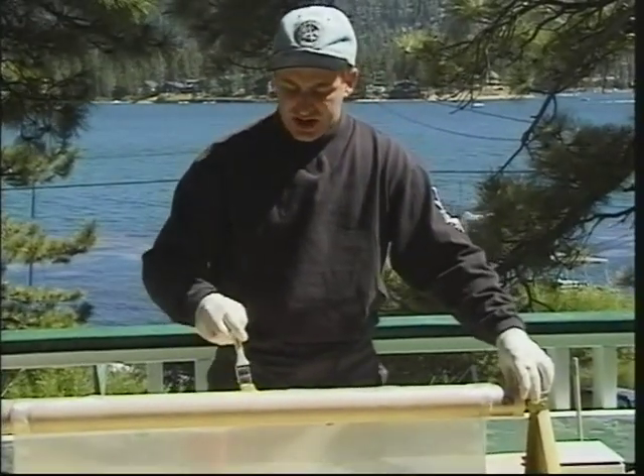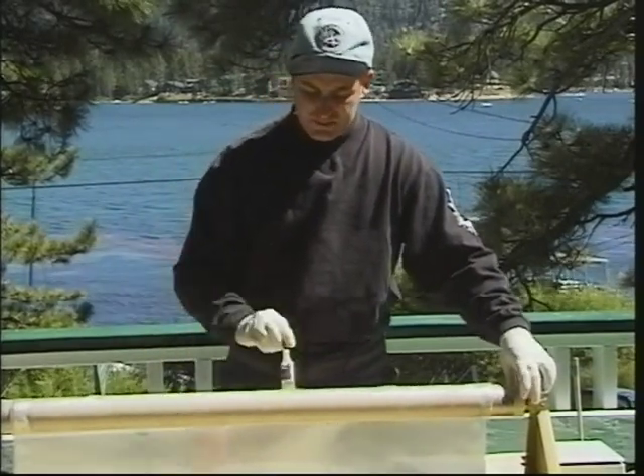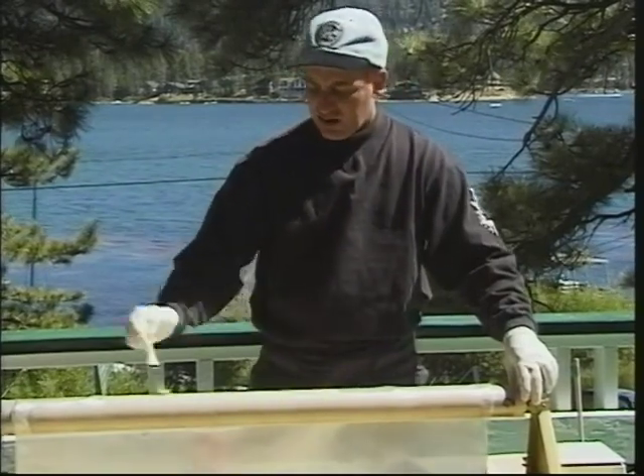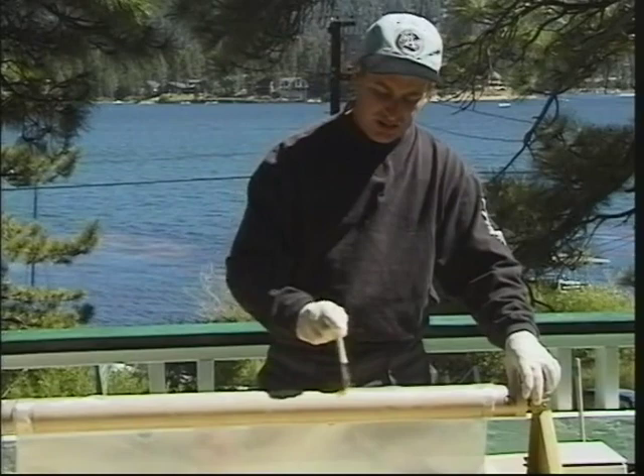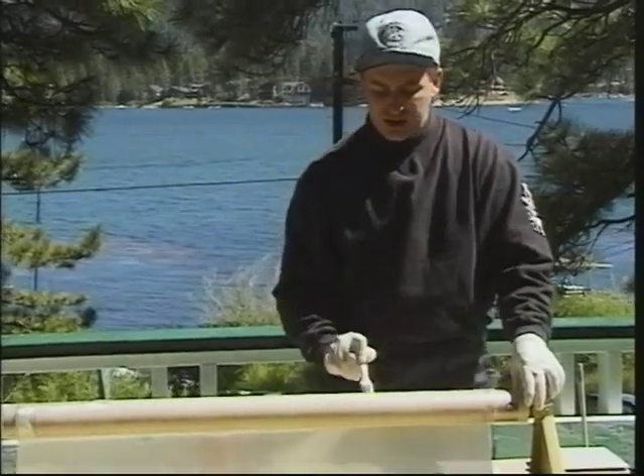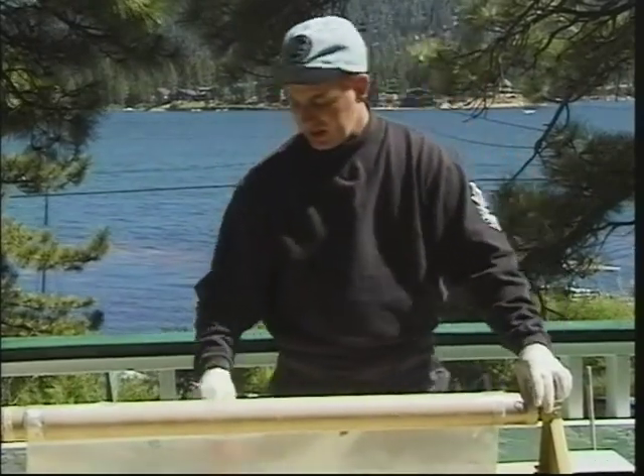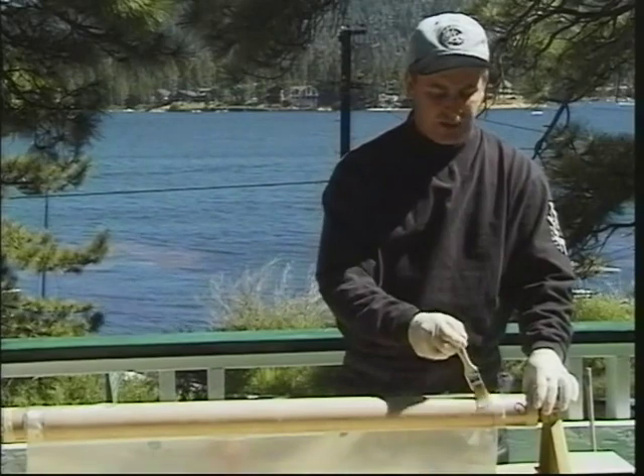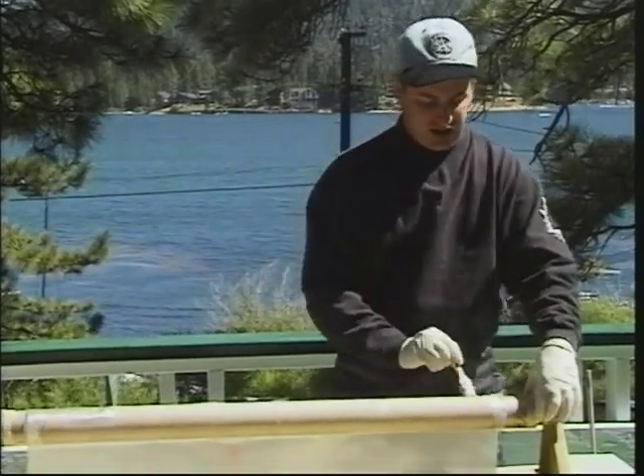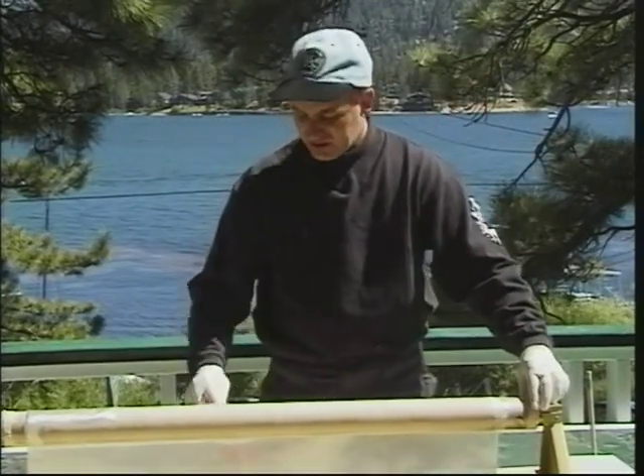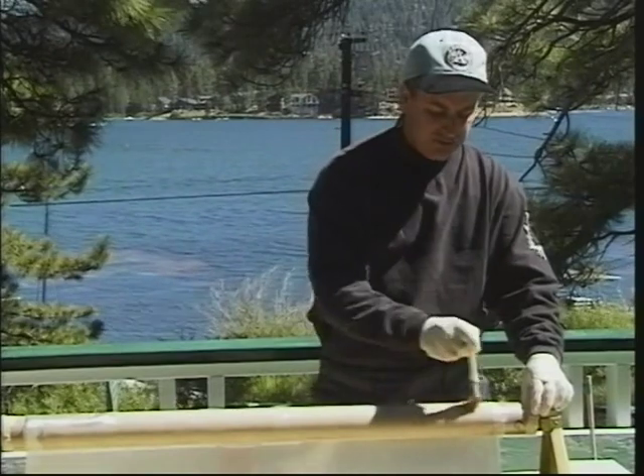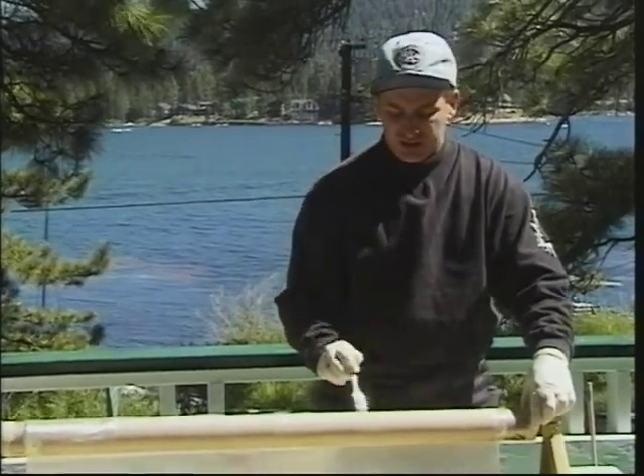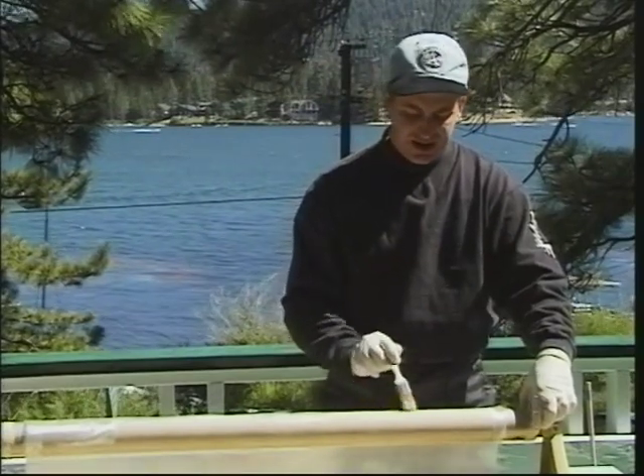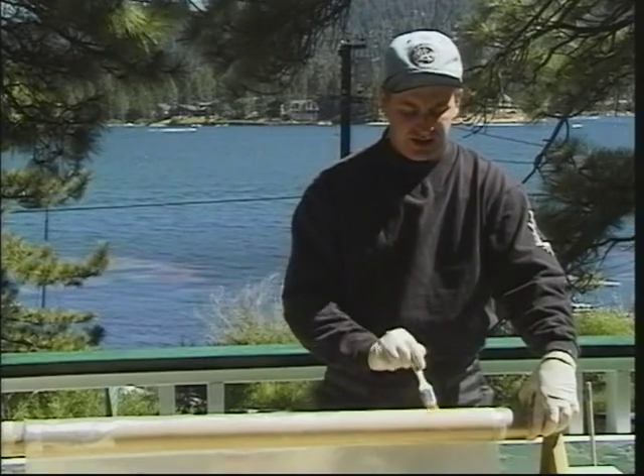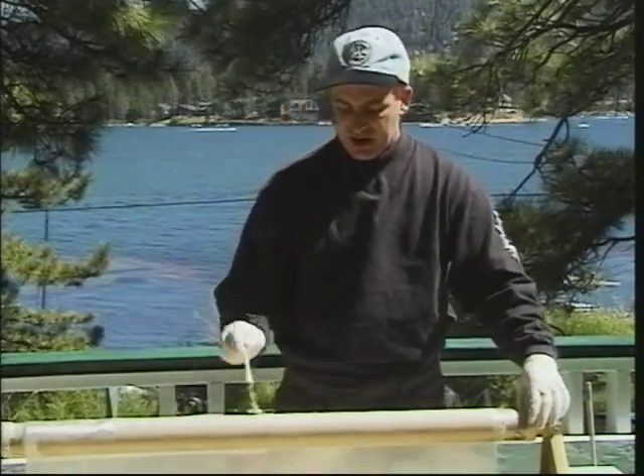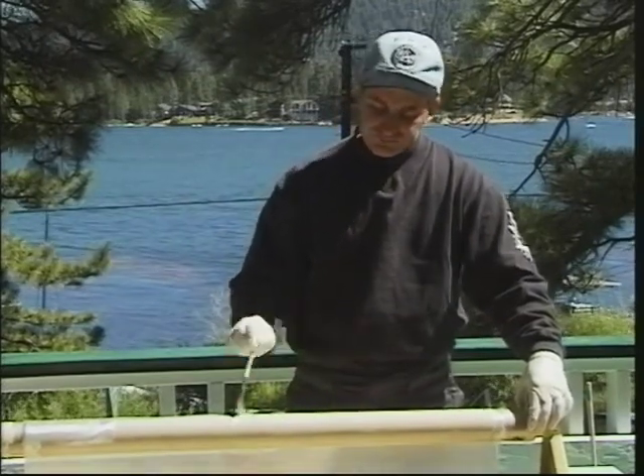There's a lot of discussion as to how many wraps of cloth you can do around a tube. When you're doing it like this, with just a dry wrap, I call it, just wrapping it around the tube naturally, and you're not going to follow it up with the heat tape winding or any vacuum bagging, try and keep it to two wraps. Now if you think you need more strength than that, go to a different material. Use a stronger material like carbon fiber or Kevlar. But it's not in your best interest to add more than a couple wraps of cloth, because those extra wraps, you're just increasing the probability that air is going to get into the laminate and decrease its strength. So it's a good rule of thumb.